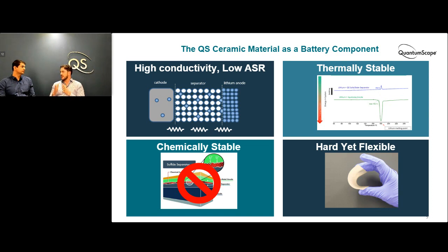But high conductivity in the material itself is not the only requirement. You also need to have low resistance with the other components in the battery. So the separator is only one component. You also have, in our case, a lithium metal anode and a cathode material, which can be comprised of different things. But your separator must have low impedance with both those other items in the battery. And it's taken us a lot of time to understand the fundamental sources of resistance that cause that ASR, that area-specific resistance between your different interfaces. But over time, we've managed to really bring that down. And today, it's almost immeasurable, the impedance between our separator and the lithium metal, which I think is a really big advantage for high-rate capability.